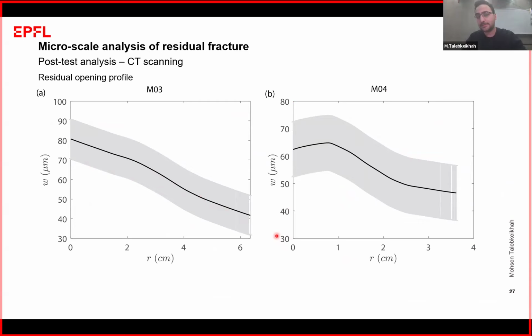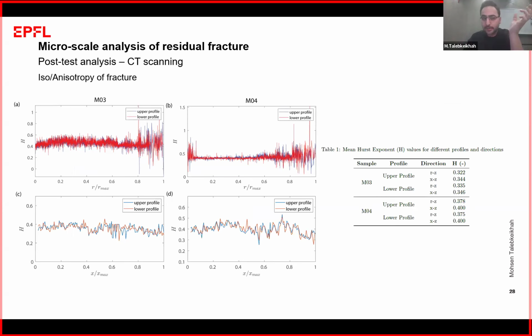But close to the tip of the fracture, I lose the resolution, so it does not reach zero at the end. But for both experiments, we could show the profile of the residual opening that remains after the experiments. We also checked this Hurst exponent, one time in the direction of the fracture propagation and another time perpendicular to it. We could see that the values in both directions are somewhat close to each other. So we can say that the fracture surface is somewhat isotropic.